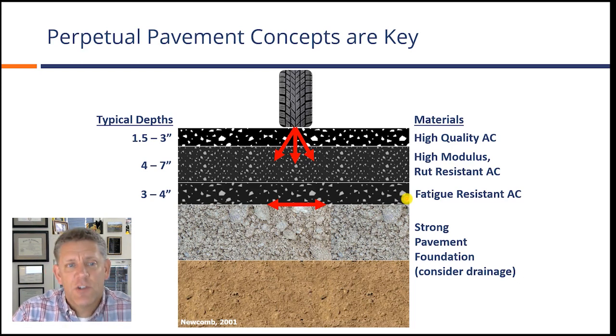So how do we achieve that in terms of thicknesses? Over here we have some typical depths, and it's very interesting that these are not overly thick. If we look at the minimum thicknesses, we arrive at about 8.5 inches total here, and on the high side about 14. You'll see in my following slides and some information that I'll be presenting in just a minute that what we see in the real world are exactly this. We're not looking at 20-inch pavements to achieve perpetual. We're looking at something in about the 8 to 14-inch range in terms of a maximum pavement thickness.